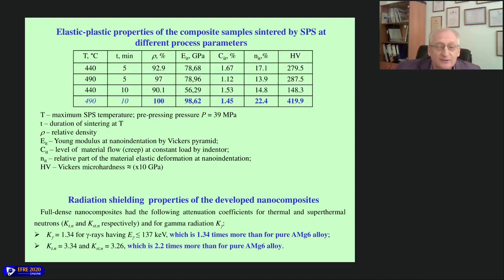This composite showed that the coefficients for thermal and superthermal neutron shielding, and the attenuation coefficient against gamma radiation, were higher than for the pure aluminum magnesium alloy as the initial material for shielding boxes.